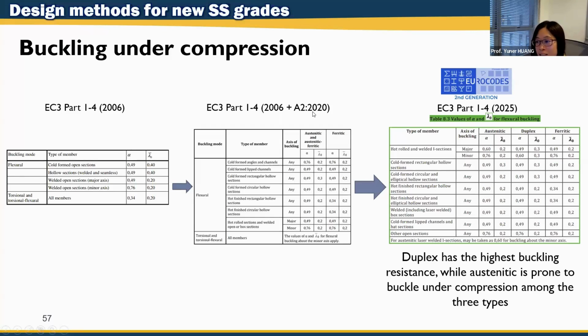However, in the amendment, the buckling resistance for ferritic is different from austenitic and duplex. So austenitic and duplex use one buckling curve. Ferritic uses a different buckling curve. And then for the new generation in 2025, austenitic, duplex, and ferritic all use different buckling curves. So that means the buckling resistance will be different if you choose a different stainless steel type. So your buckling resistance needs to be calculated based on which stainless steel grade you choose. After comparison, we realized duplex has the highest buckling resistance. So if your member is buckling sensitive, then duplex will provide the best performance, while austenitic is prone to buckle under compression among these 3 types.